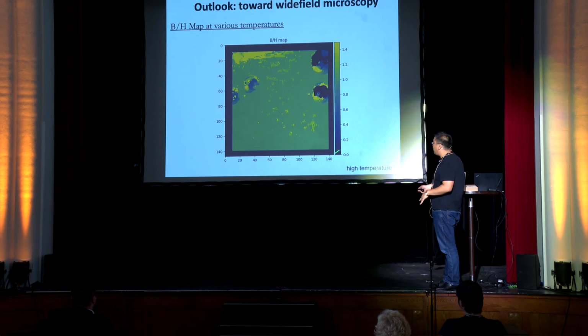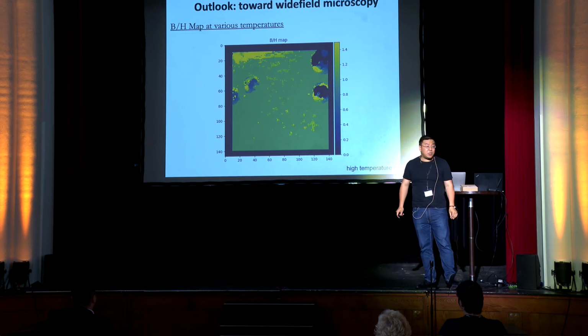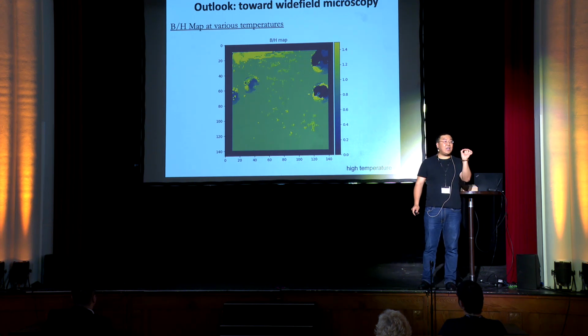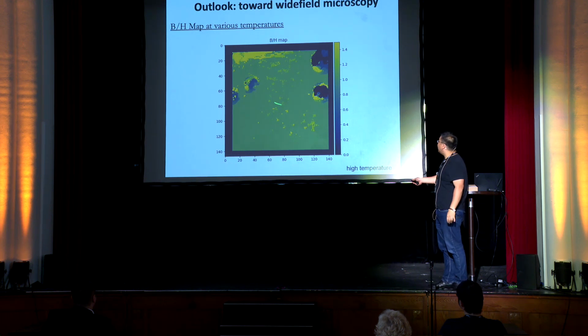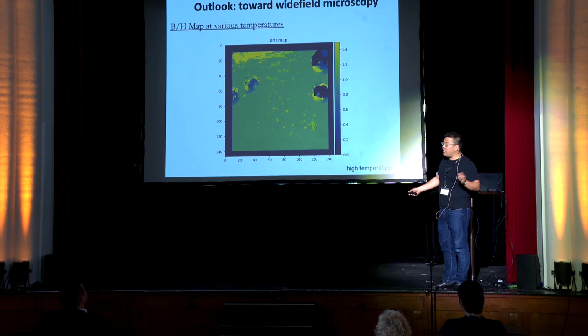So this is microns on both the X and Y scale. The sample is somewhere hiding here, but this is at high temperatures above the transition temperature of BSCCO. It's not an optical image in any way. All I'm plotting here is the magnetic field measured by NV centers divided by the applied field. This kind of greenish color is about 1. So aside from rubies, which you can kind of see here mess up the measurement a little bit, you basically see no evidence of the sample.